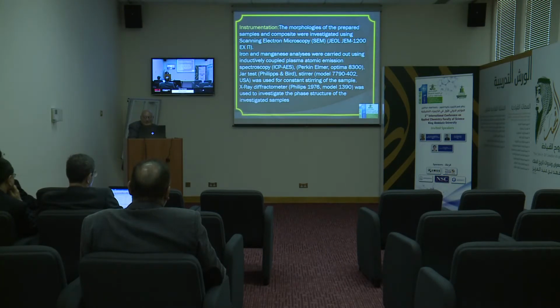metal ions. This work has been published, as you see, but the present work aimed at increasing the removal efficiency through the formation of organocomposites using starch, first of all, then developing the method through the use of carbon nanotubes clay composite, which has achieved the best removal up to 99% for both elements.